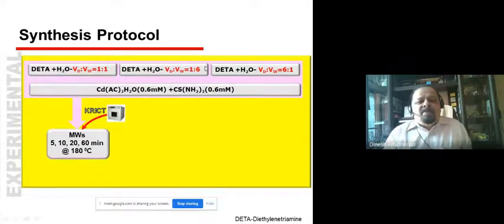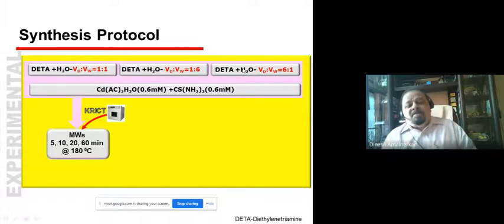Here the whole idea is, after this part was all fine, we had followed the research from the Chinese researchers. The Chinese researchers had just taken cadmium acetate and thiourea in the same millimolar proportion, mixed with diethylene triamine and deionized water in a certain volume ratio, put it in an autoclave, exactly similar to us. But they heated their pressure cooker using a conventional heating mechanism, which took 12 hours to get the desired morphology at 180 degrees centigrade.